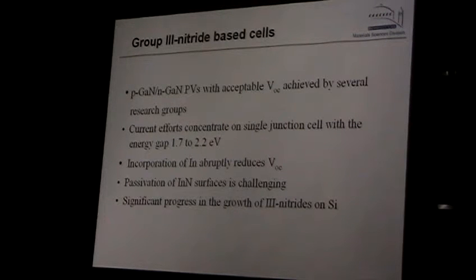So let me finish this part. We developed several ideas about how to use gallium-indium nitride, gallium nitride type of solar cells, and currently most of the effort in the world concentrates on making solar cells with the energy gaps about 1.7 to 2.2 electron volt. This is where you can use them in tandem with other systems and also with silicon. There are some issues still there, and the surface, as I mentioned, surface inversion is a significant issue for this, but there are people working on ways of passivating the surface.